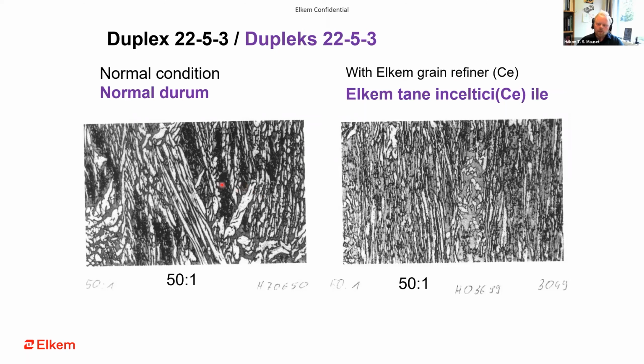So these are not the best pictures, but at least here you see this was the normal structure they had in their forged components. And then with the Elkem, when they started to use the Elkem grain refiner, this is how it looked. So we see that the spacing between the ferrite grains is much narrower when they started to use the Elkem grain refiner. So there is a definite grain refining here.